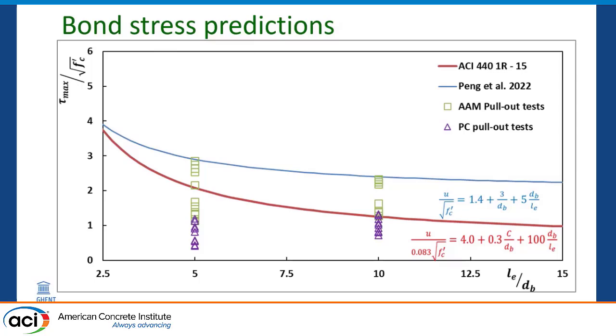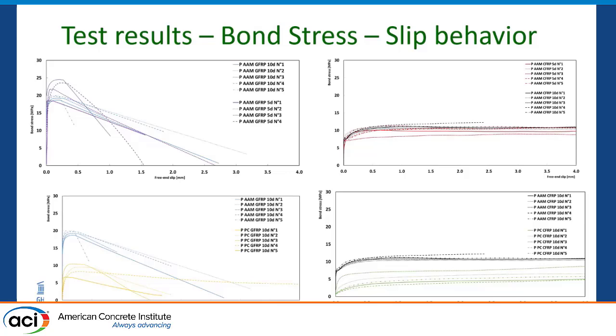So there is also another line from the research study from Ghent, that they actually investigated FRPs bonded with alkali-activated mortar, and their prediction didn't take into account the position of the bar, and they actually overestimated our results. So here we can see bond stress versus slip behavior.